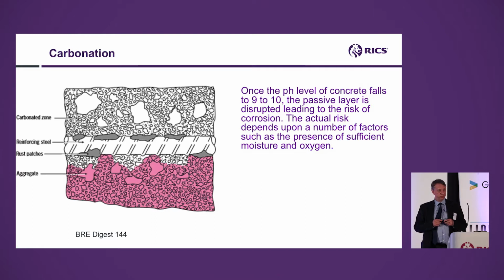When the zone of carbonation has reached the steel, it doesn't mean that corrosion will occur. What it means is there is a risk of corrosion. So the first question really is, is carbonation disrepair? And you will often go out, when conducting a survey, and measure the depth of carbonation and also measure the depth of cover to see whether the steel's in the carbonated layer, whether there's risk, whether it's approaching it. It's particularly important for chlorides. I'll come back to that in a minute. If you've got a rebar close to the corner of a beam or something, it's got attack on two fronts, so it may be more vulnerable. If you've got cracks in the surface, the zone of carbonation goes further in, and you might end up with damage around the reinforcement part.